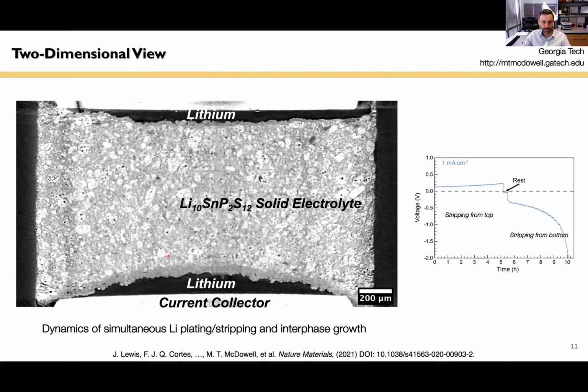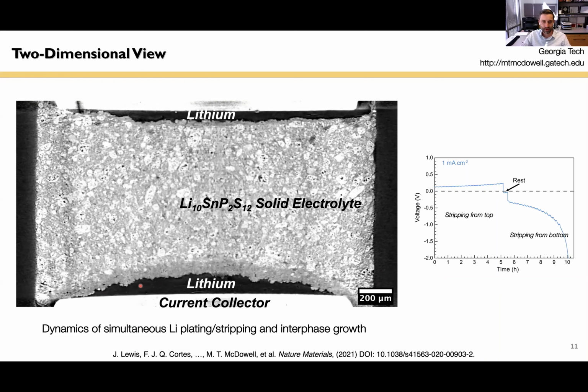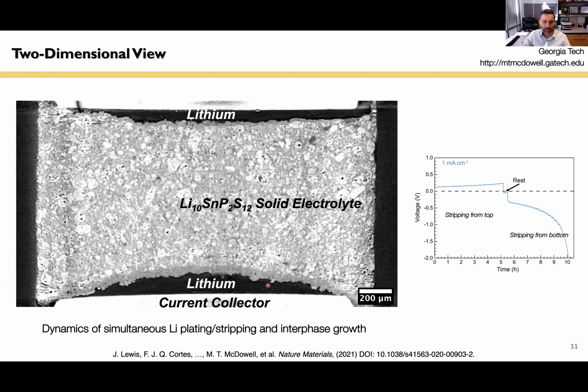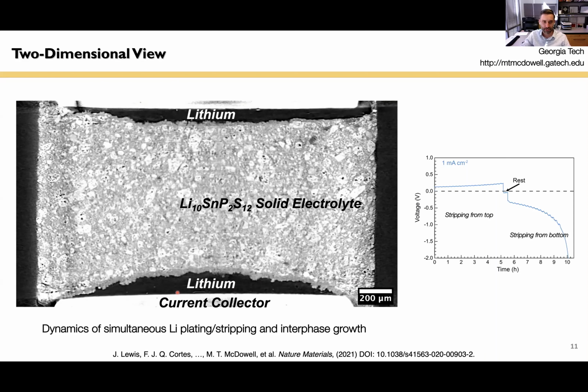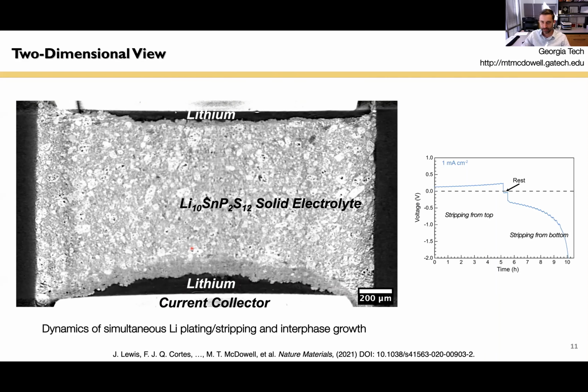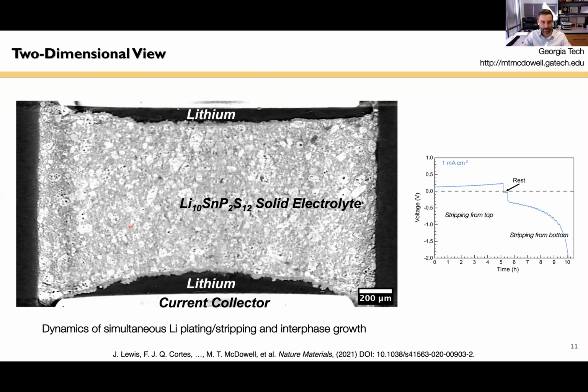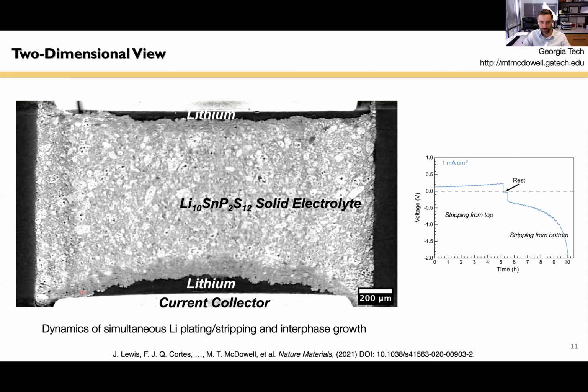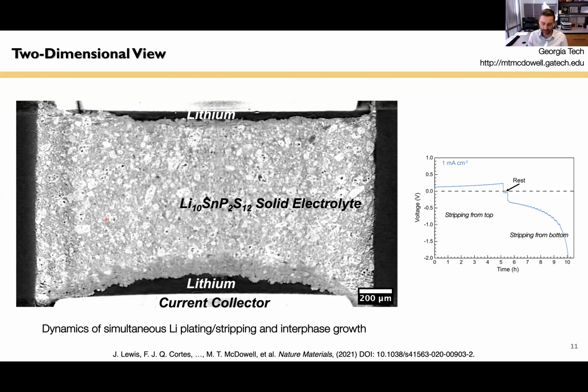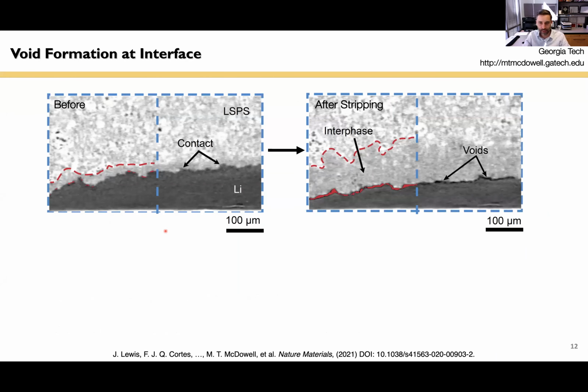But we did a lot of work on this to segment out these various volumes, and we found that actually the lithium is being stripped very effectively during stripping, but during what we would refer to as deposition normally, we're not actually depositing lithium, we're just growing interphase. So I think that this video is kind of useful to understand the basic dynamics of what's happening in our system. But what was really interesting is we were able to analyze this data in more detail. And we found that, in fact, after stripping the lithium, we often saw the presence of voids at the interface.